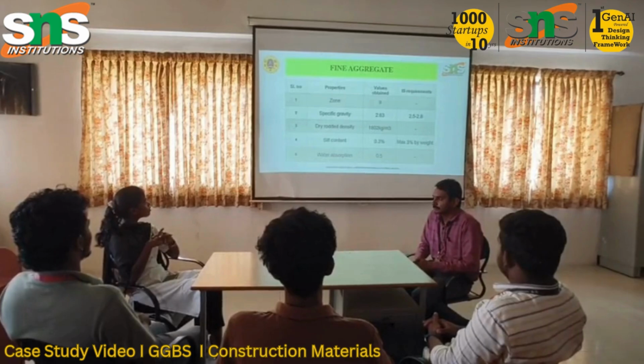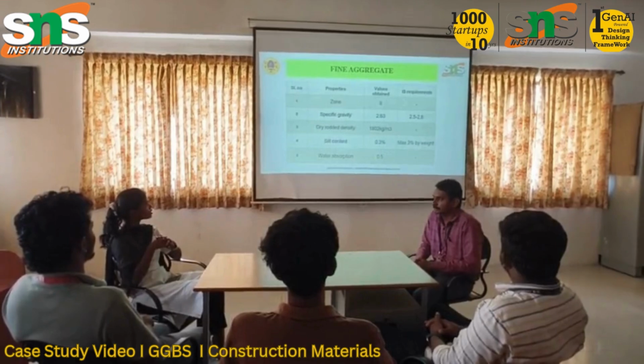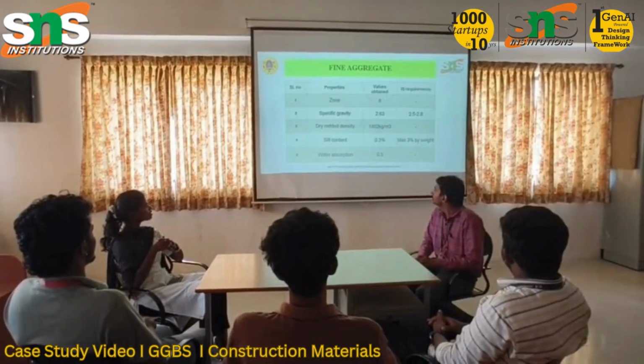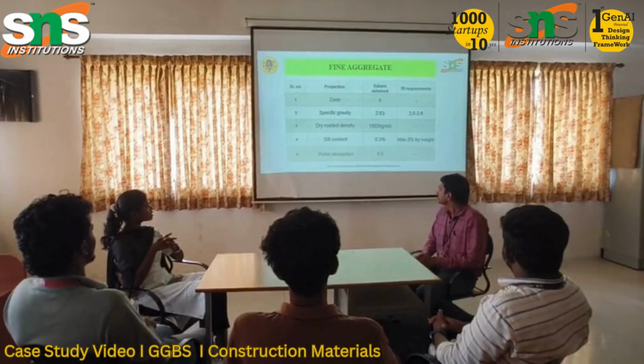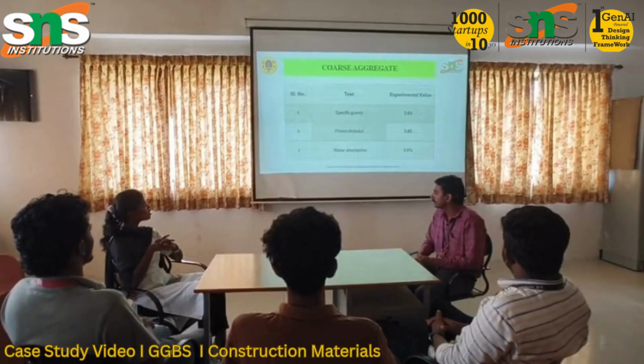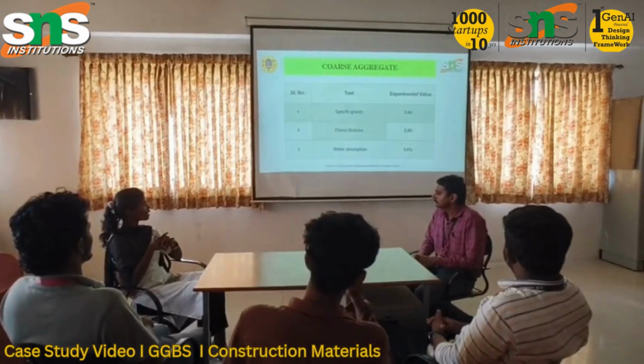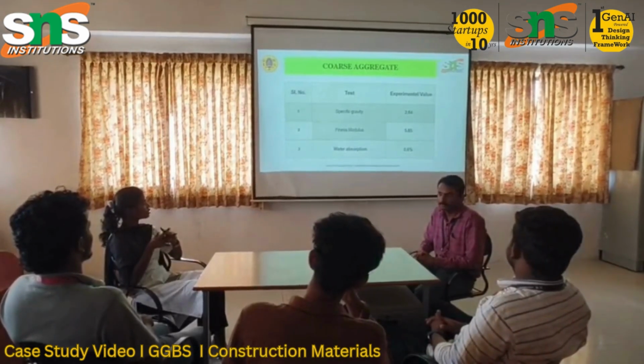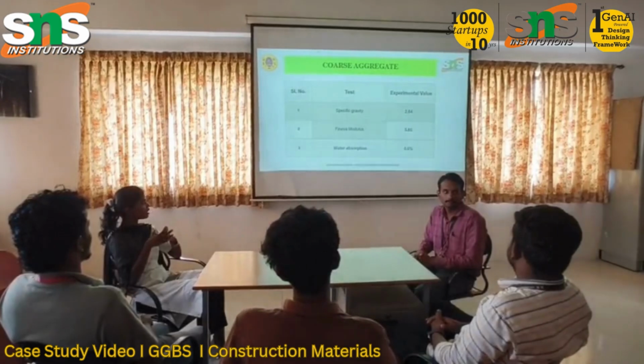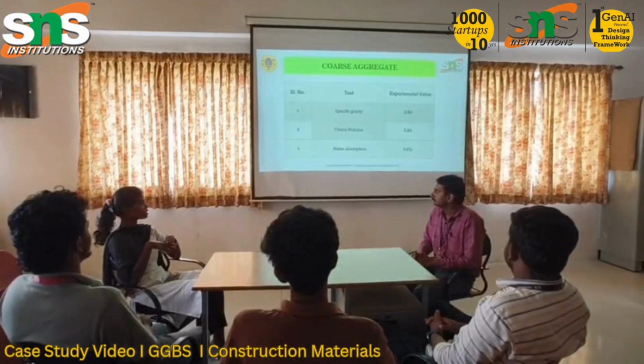For the fine aggregate, we got zone 2, and the specific gravity of the fine aggregate is 2.63. The dry rodded density is 1802 kg per meter cube, and the silt content is 0.3%. The water absorption is 0.5%. For the coarse aggregate, the specific gravity is 2.64, the fineness modulus is 5.85, and the water absorption is 0.6%.